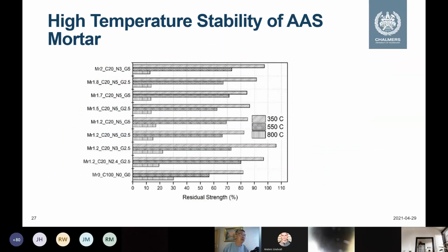For fire resistance, that is a little bit different. So you can see, let me say, this is Portland cement, 100% cement. So with 350, 550, and 800. So after 800, the residual strength for Portland cement is about 80. No, this is wrong. This is 350.